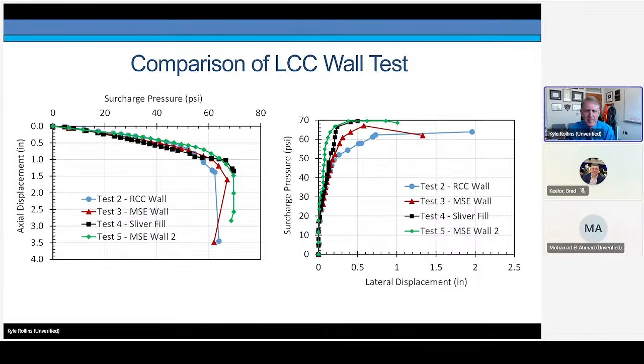On the left is axial displacement versus surcharge, and on the right is lateral displacement versus surcharge. You see more variation in the lateral displacements, but overall the behavior, especially axially, is very consistent. And this to me is quite surprising, considering the fact that, as I pointed out earlier, there's a lot of variation in the strengths that we get from the various tests. And even with the sliver fill, we still get a lot of resistance, similar resistance with a wall that has lower strengths. We're still getting a good behavior.